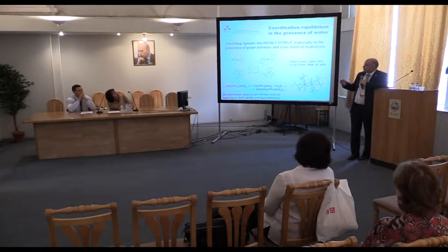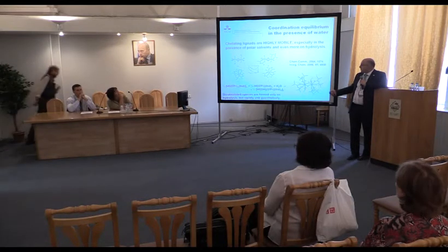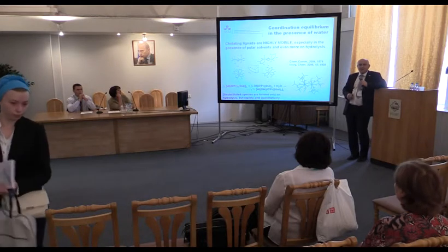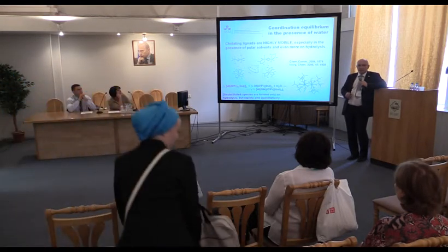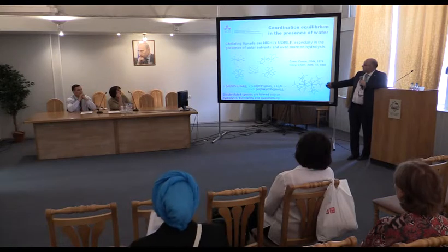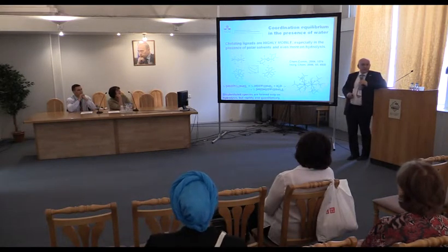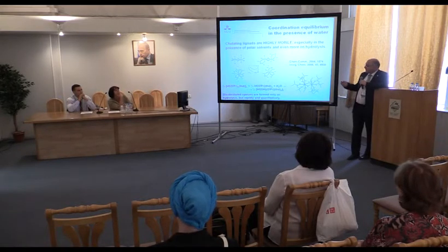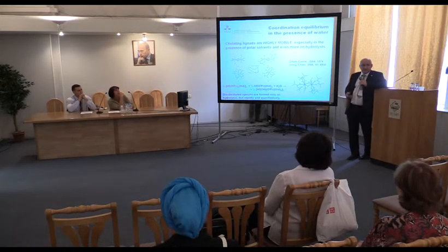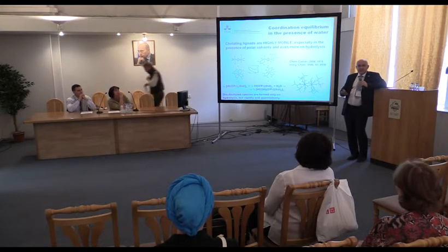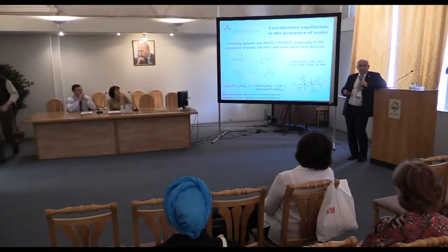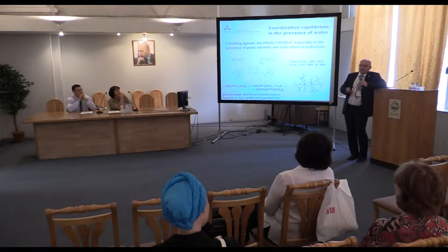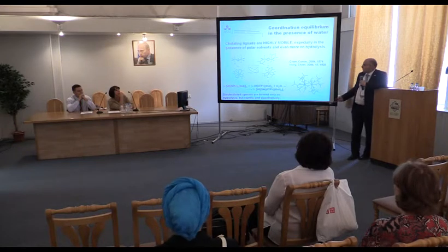So Ulrich Schubert was usually postulating, you can see in several reviews, that these chelating ligands are decreasing the kinetics of hydrolysis and condensation, and his idea was also that they are sitting still on metal cations. This is simply not true. They're very quickly moving, and kinetically they are increasing their reactivity. The effect of chelating ligands is that they simply are stabilizing the species which are formed, these nuclei, these metal oxide nanoparticles in solution.